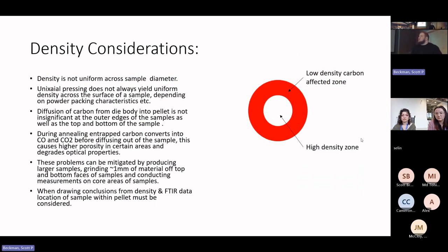So for our density calculations or measurements that we'll show later on, there are a couple of important considerations that you need to be aware of. What we found a lot of the time was that during the sintering process, because we were sintering in a high carbon environment in a carbon die, there was actually diffusion of carbon into our final sintered product, which then would later come out during the annealing process and leave vacancies and decrease the density of our product. And the important thing to remember is that we basically produced one large chunk for each of our compositions and sintering conditions, and then broken into smaller chunks that were then annealed and had post-treatments done on them. But depending on where that final chunk that was heat treated came from, it'll be differently affected by the amount of carbon that diffused into the actual pellet. So if the chunk that we chose to do annealing on happened to come from the outside edge that had more carbon diffusion, that has an artificially lower density than a chunk that would come from the center of the pellet that would have less carbon diffused into it.